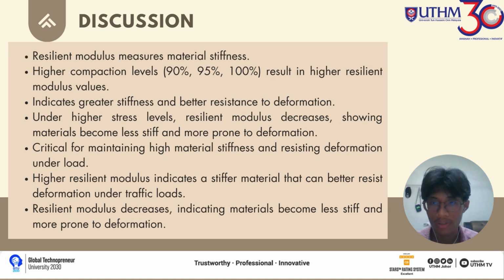Discussion for Figure 4: resilient modulus measures material stiffness. Higher compaction levels, which are 90%, 95%, and 100%, result in higher resilient modulus values. This indicates greater stiffness and better resistance to deformation. At higher stress levels, resilient modulus decreases, showing the materials become less stiff and more prone to deformation. This is critical for maintaining high material stiffness and resisting deformation under load. A higher resilient modulus indicates a stiffer material that can better resist deformation under traffic loads. When resilient modulus decreases, the materials become less stiff and more prone to deformation.